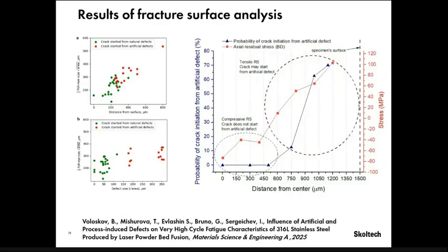We relate it to the residual stresses. As I told, we measured it. So for machined specimens, residual stress is still comparably high. And the red line here is residual stresses. This is the center of the specimen, and this is the surface of the specimen. And we can see the high compressive residual stress here and the tension here. And the blue line is the probability of crack initiation from the artificial defect